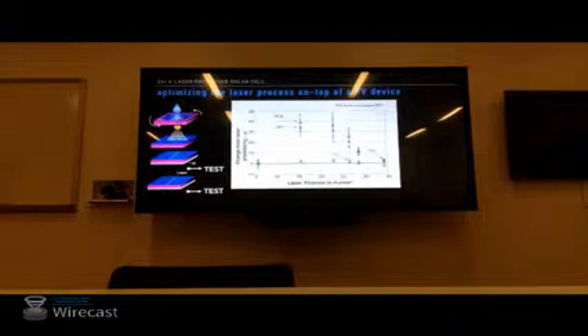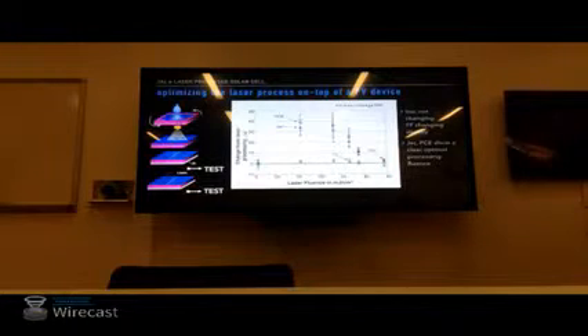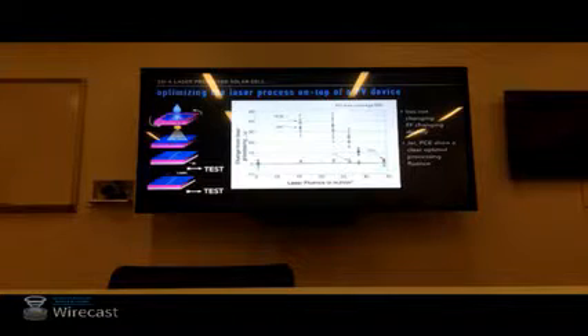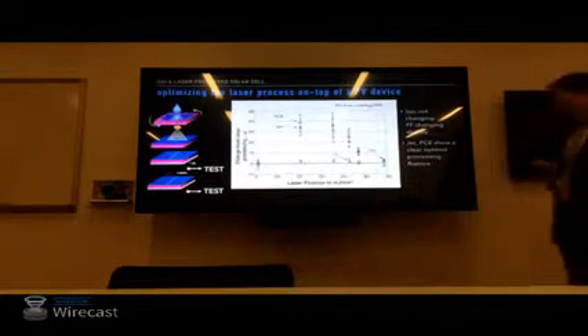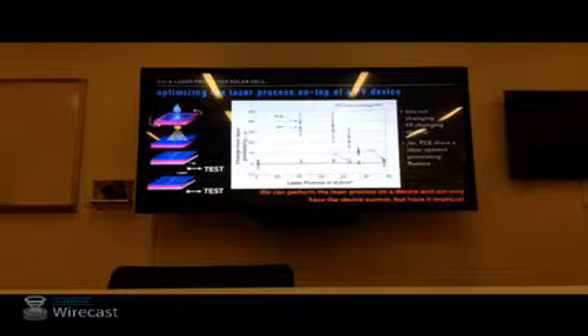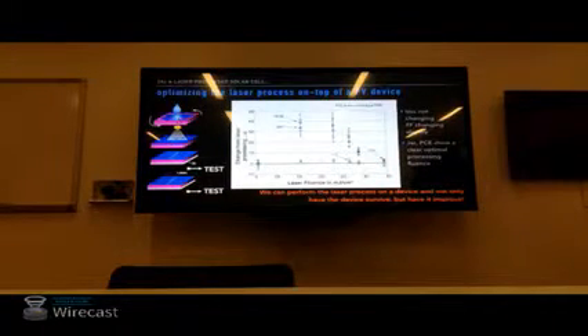So if we look at this purposely bad device that we expect to see large changes, in fact we do. So if we track those metrics which I just discussed, we see a clear region where we have great enhancement to our short circuit current and our power conversion efficiency. So we can use this information to prescribe an optimal processing of, say, 15 to 25 millijoule per centimeter square. And now we've answered one of our questions that we sought out to answer: can we do our laser process on an otherwise completed solar cell? And yes, right here we have, and we've actually made this already bad device perform much, much better. You know, we're reaching almost 50% enhancement to efficiency.